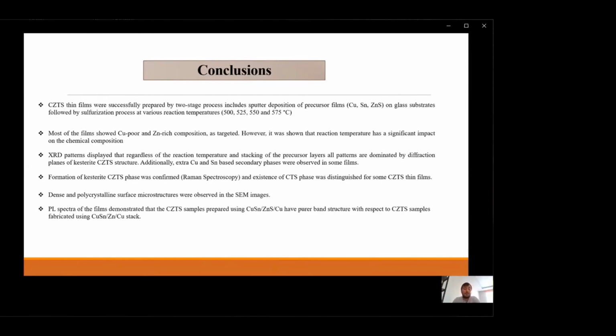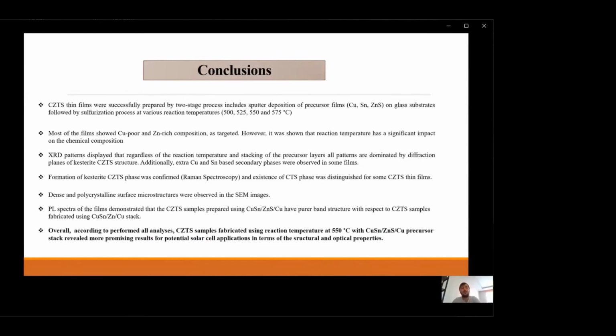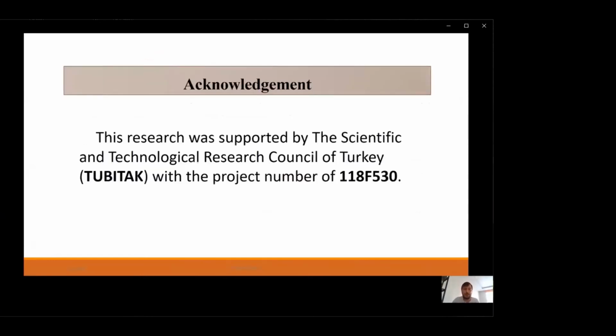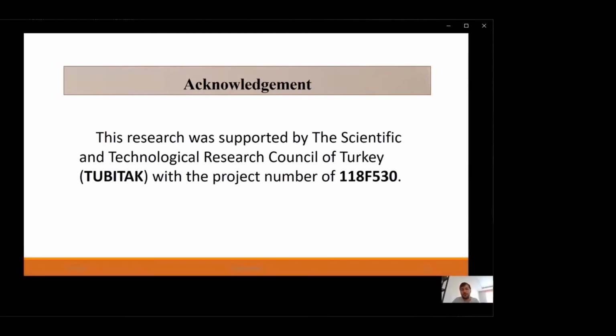PL spectra of the films demonstrated that the CZTS samples prepared using A-type have a purer band structure with respect to other samples. Overall, according to the performed analysis, CZTS samples fabricated using a reaction temperature of 550 with the copper-tin-zinc stack revealed more promising results for potential solar cell application in terms of structural and optical properties. Our special thanks to TÜBİTAK, because this research was supported by the Scientific and Technological Research Council of Turkey with this project number.